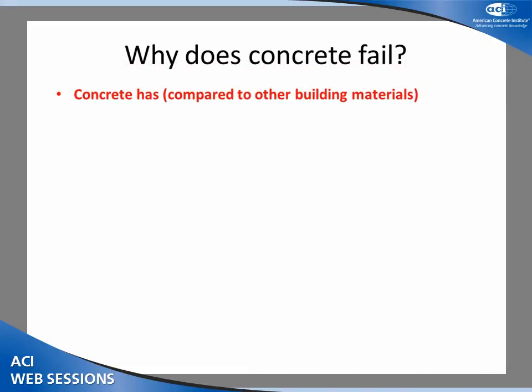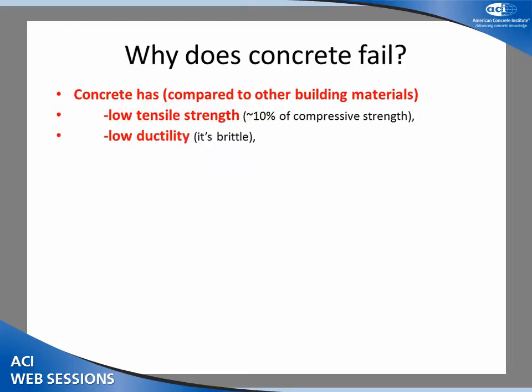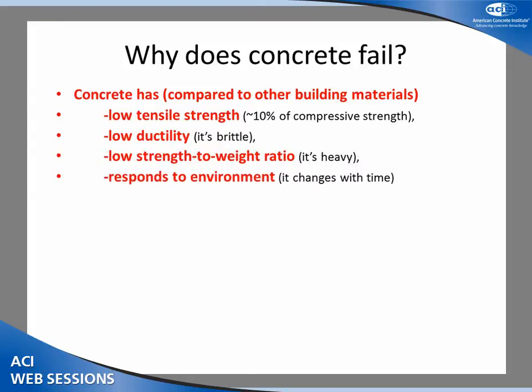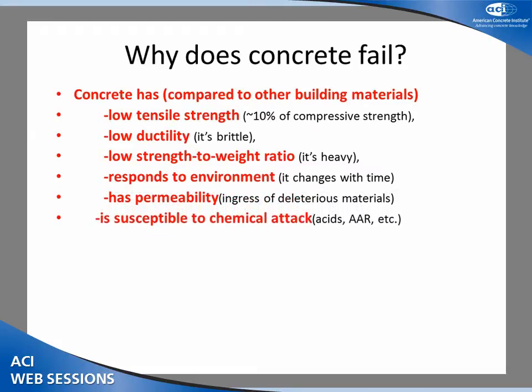So, concrete has some Achilles heels. It's not a perfect material. It's relatively low tensile strength. It's about 10% of its compressive strength unless you do some funny things like put fibers in it. Low ductility, it's brittle. It's really heavy for as strong as it is. It changes with time, responds to its environment. Has permeability. It's a hard, wet sponge. And it doesn't like certain chemicals, especially acids. And it cracks. That's the most common failure mechanism for concrete, it's cracking.